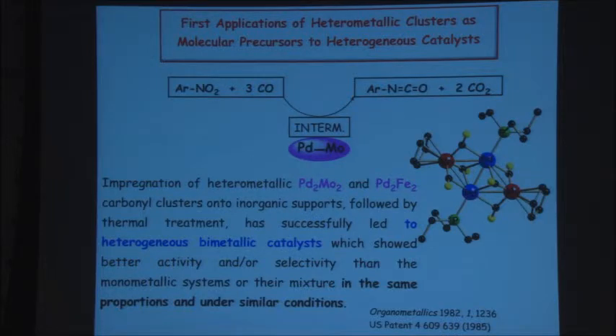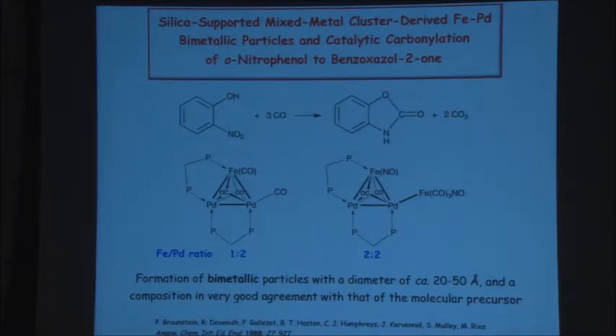And then we did the same approach with iron palladium catalyst, which from the patent literature was also employed for conventional heterogeneous catalyst. You mix the salt, you stir palladium chloride, molybdenum oxide, you stir, cook, etc. But here we have a molecular-based approach to the system. So in other words, that can be actually applied to the formation of new heterogeneous catalysts. These are the iron palladium precursors that we use. You can see we can modify the palladium to iron ratio, 1-to-2, 2-to-2. And here we extended that to an organic derivative, which is the ortho-nitrophenol, which gives this heterocycle, benzoxazolone. And again, we found a much better activity and selectivity using the cluster-derived heterogeneous catalyst.